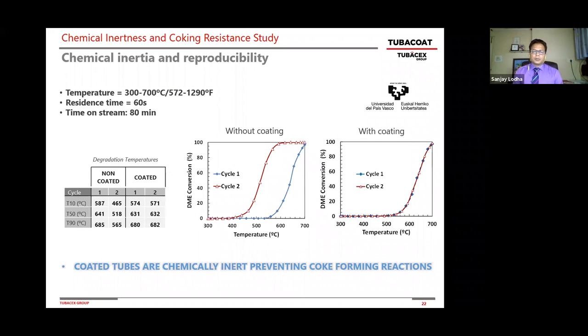So what we show in this particular slide is an experiment done at the university in a furnace heater. We have multiple cycles. What you see here is one heater without the coating, the other one with the coating. Cycle one, if you look at T10 conversion for the non-coated tube, the temperature is 587 degrees. And then when you shut down and start again, T10 starts 100 degrees earlier, which indicates you're promoting the carbon forming reaction because the metal surface takes an active part in promoting the carbon forming reaction.